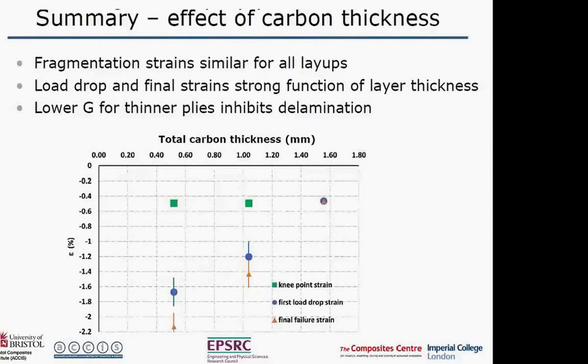So just as we saw in tension, we have thin carbon plies, 1 or 2 in this case here, and we get it going beyond the fragmentation and we get this delamination occurring. But when we have thicker blocks, it just presumably delaminates and then fails in compression straight away as soon as it starts to fragment.